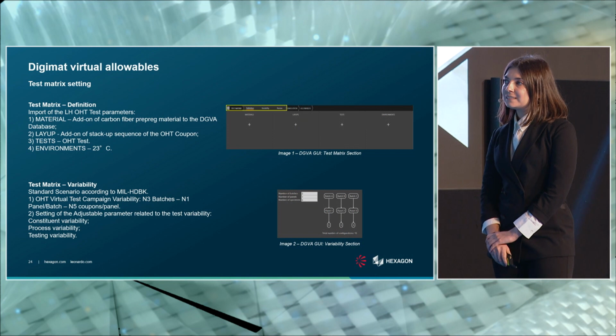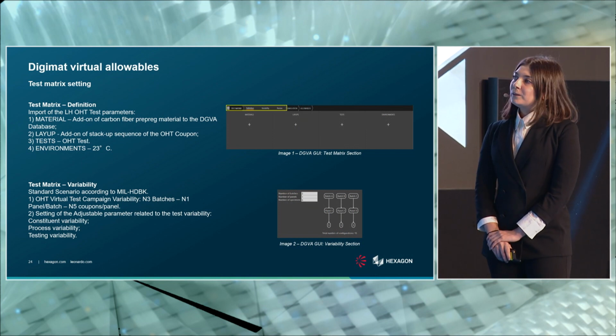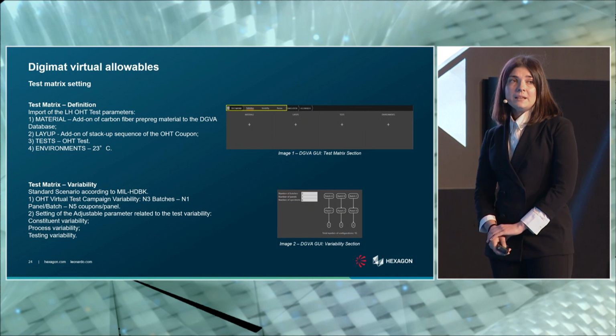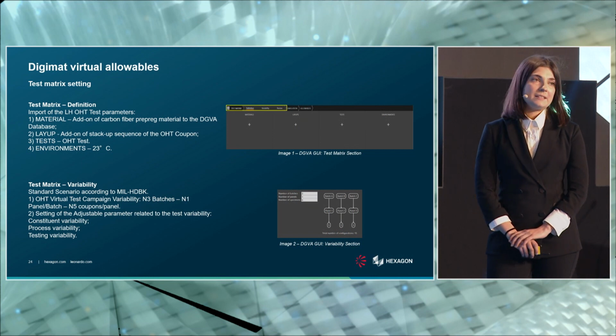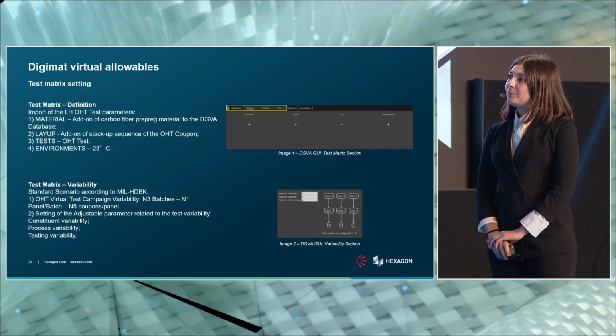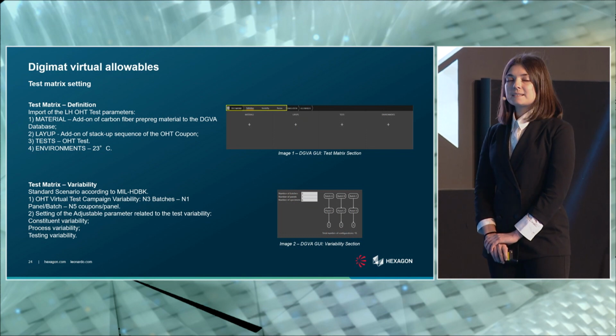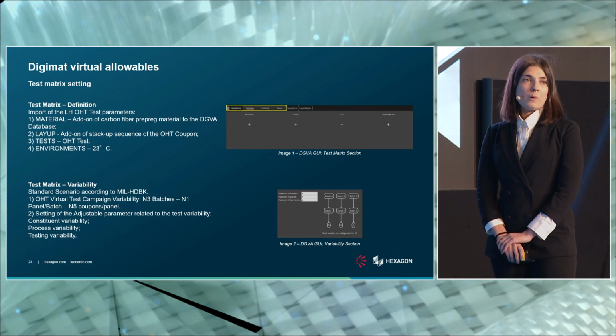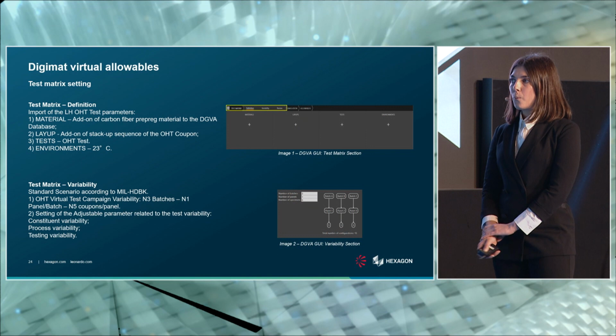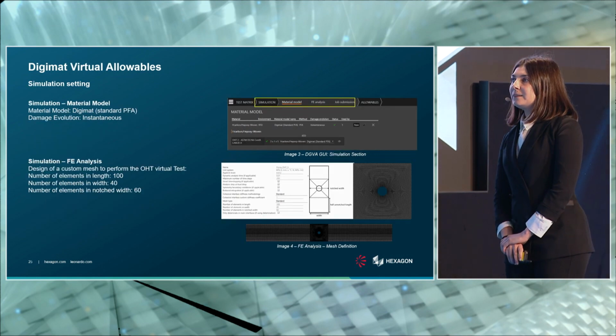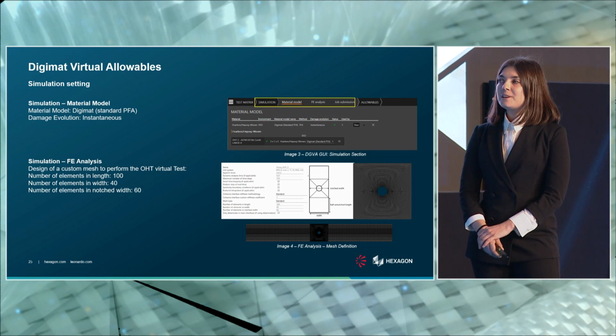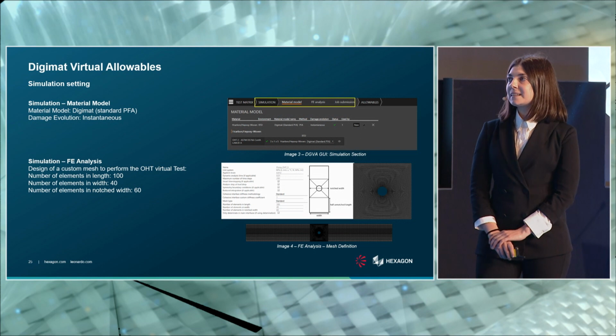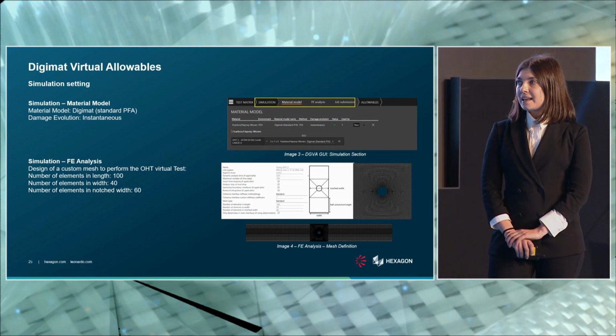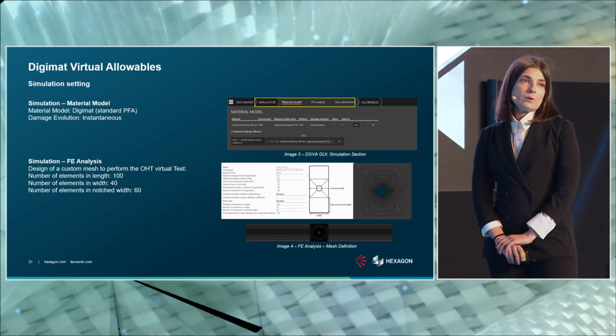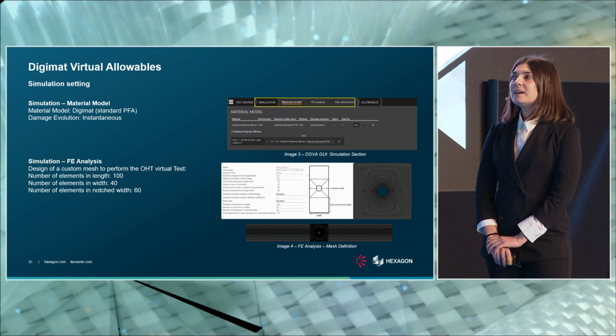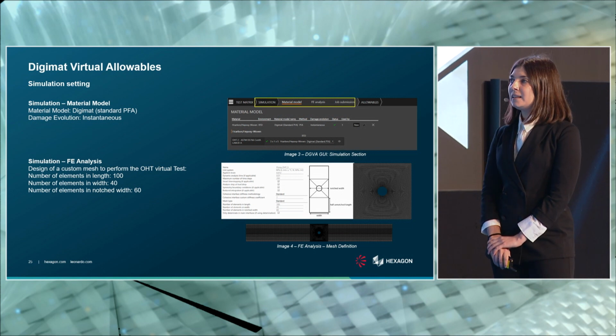In the second part, the user has to choose the variability of the test campaign. In this case, we are going to simulate a totally virtual test campaign of 3 batches, each one with 1 panel and each one with 5 coupons. Then we have to set the FE analysis parameters, and for this OHT test, we choose a custom mesh with 100 elements in length, 40 in width, and 60 in notched width.